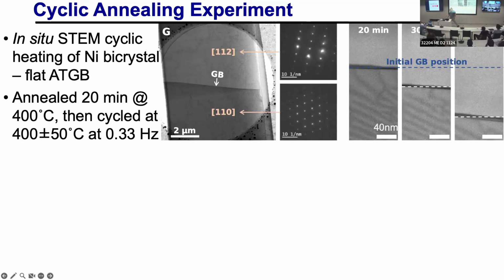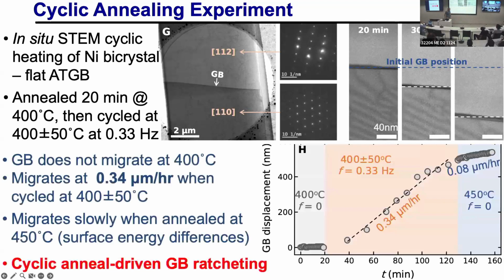So the total distance it's migrated, I didn't write it down here, but let's see. So this is half a micron right here. This is the grain boundary displacement as a function of time. And first they hold it at 400 degrees C for a while, and the boundary doesn't move. It's a flat boundary, the temperature is relatively low. Then I put on the oscillatory driving force, plus or minus 50 at this frequency. And the data is not perfect. This was the first experiment on the thermal cycling.